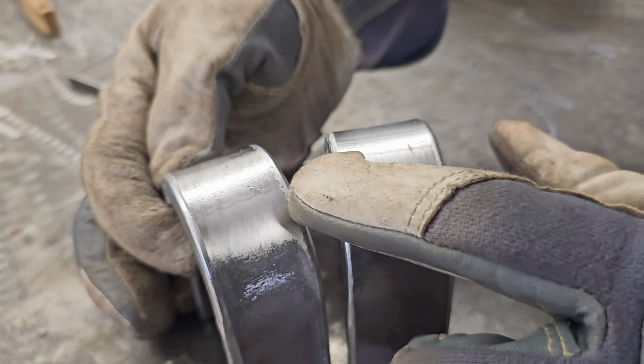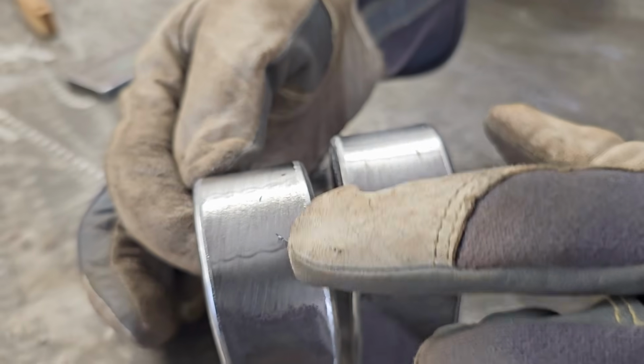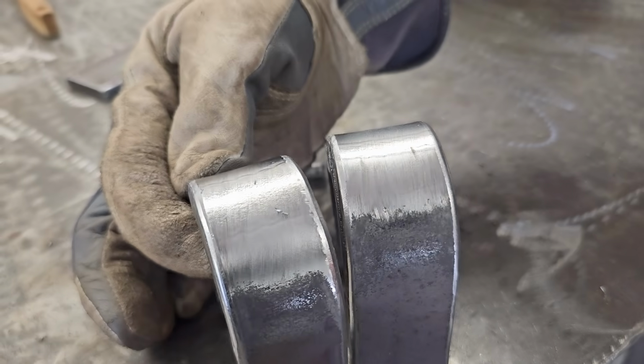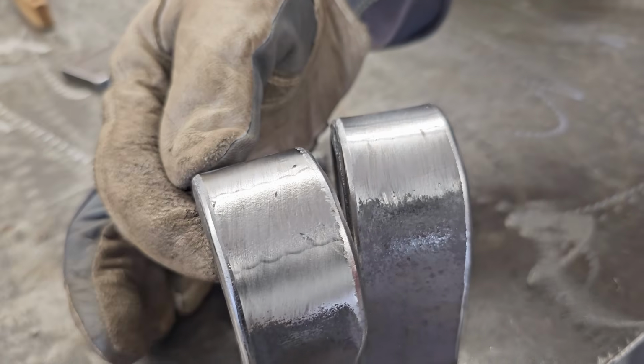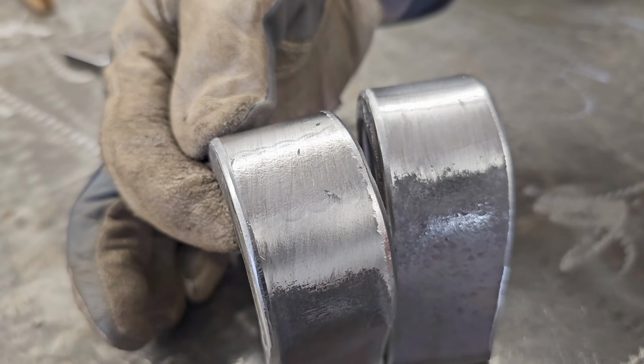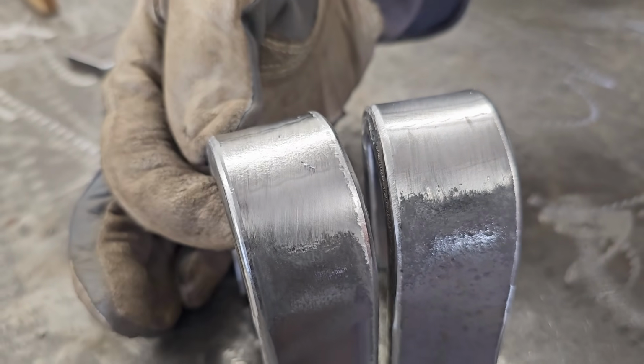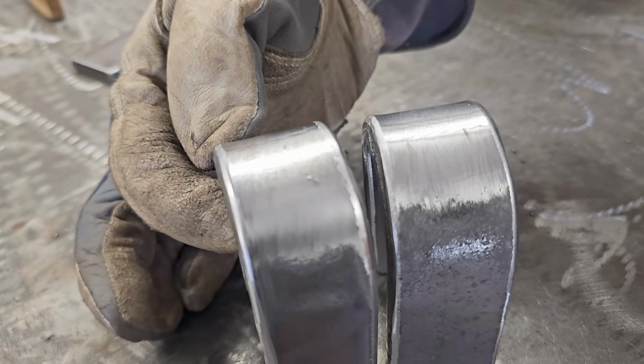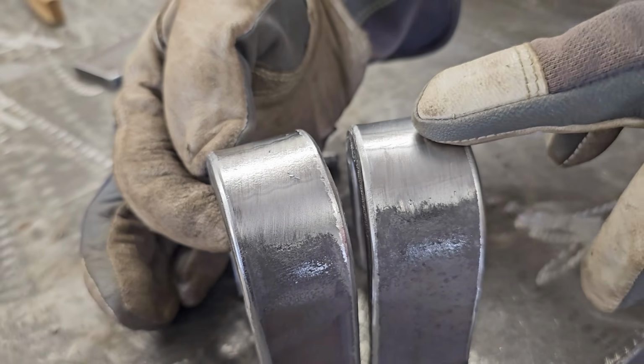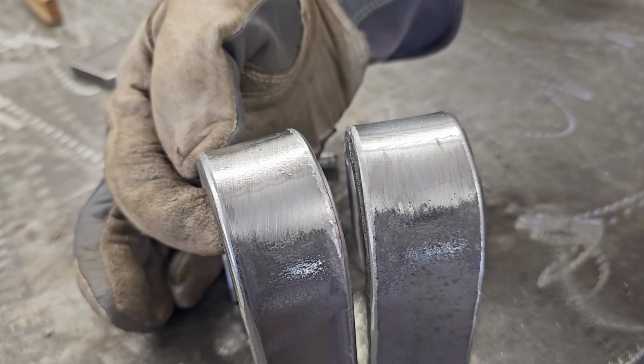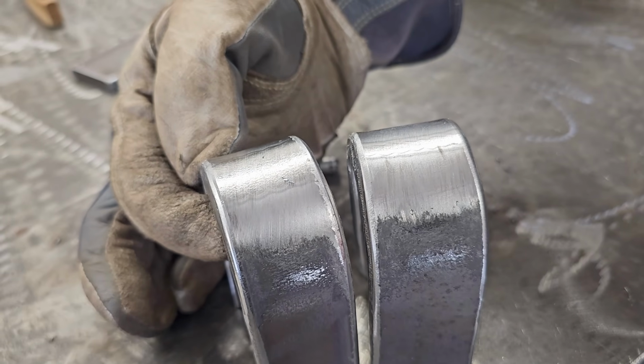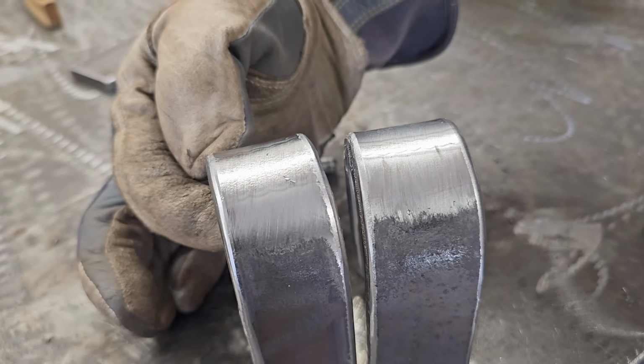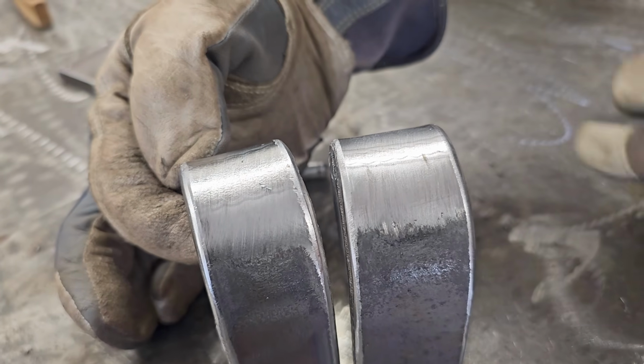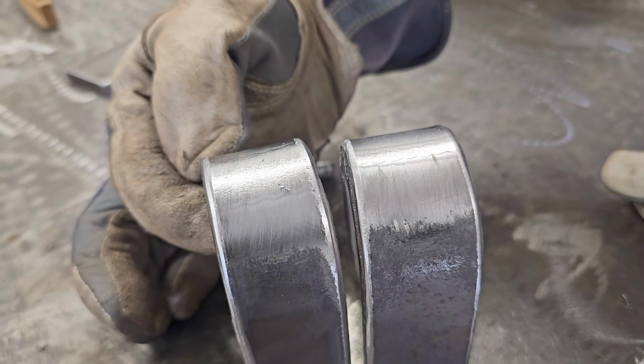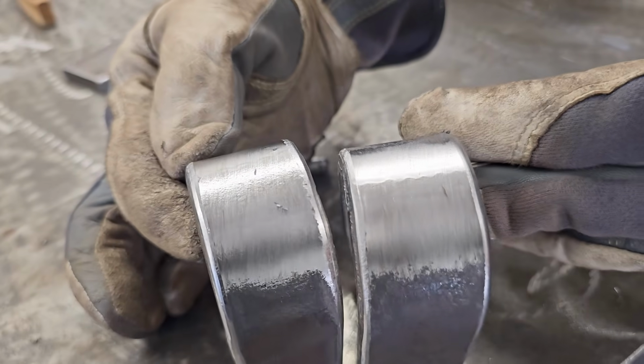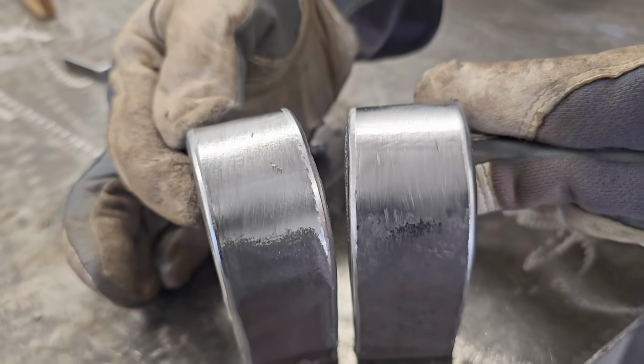On the face here, there was some low spots that you can still see, but those aren't really discontinuities. They're just low spots, and they just stretch out a little bit, but they don't open up to reveal any type of discontinuity. So that's what we're looking for, something that opens up, either lack of fusion, porosity, or if it was a flux type process, maybe a slag inclusion or something like that. But these are pretty clean, so this would definitely be a pass.